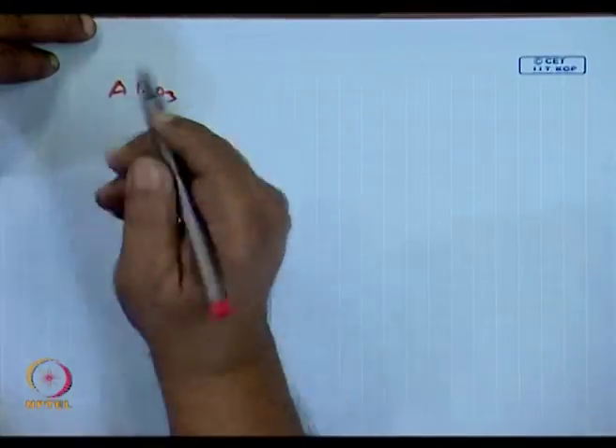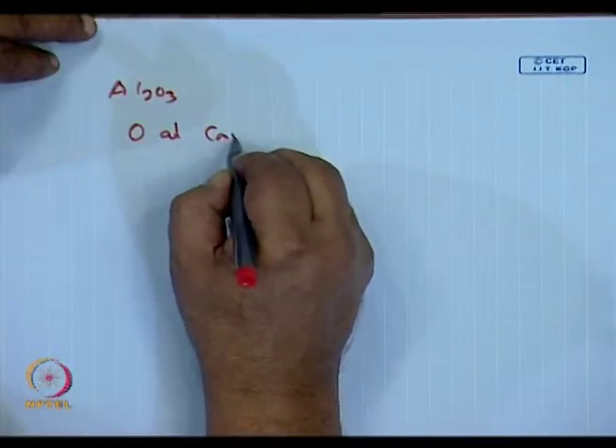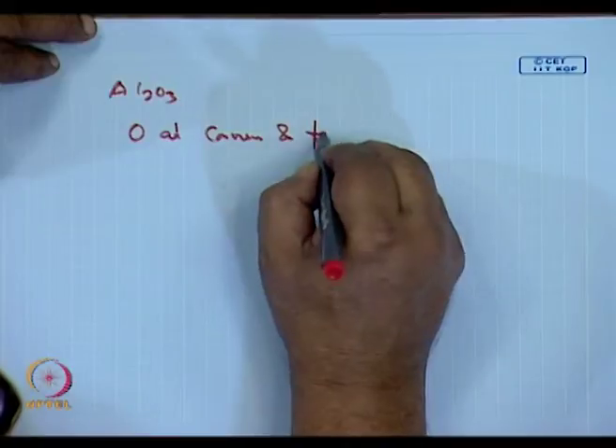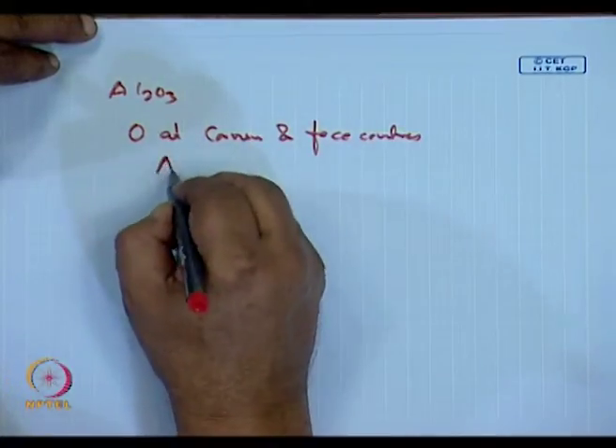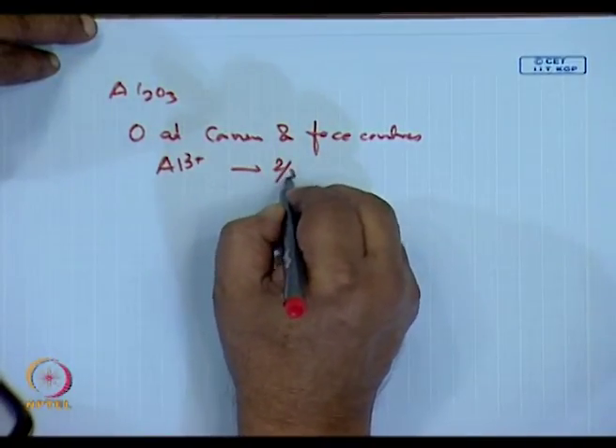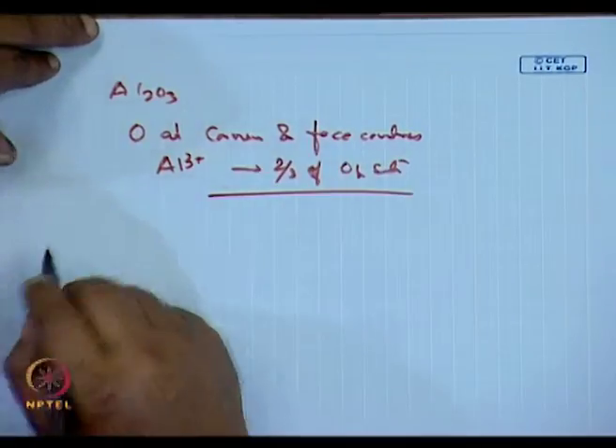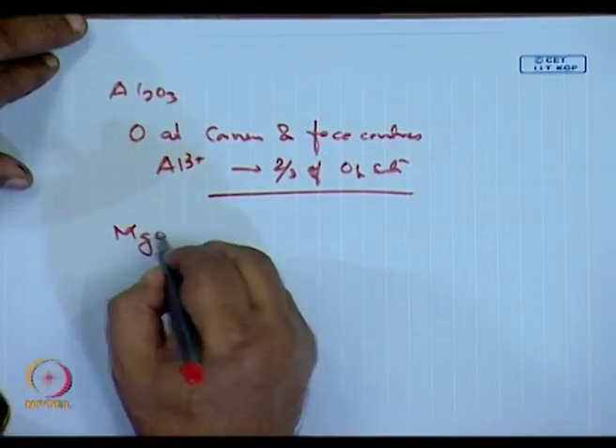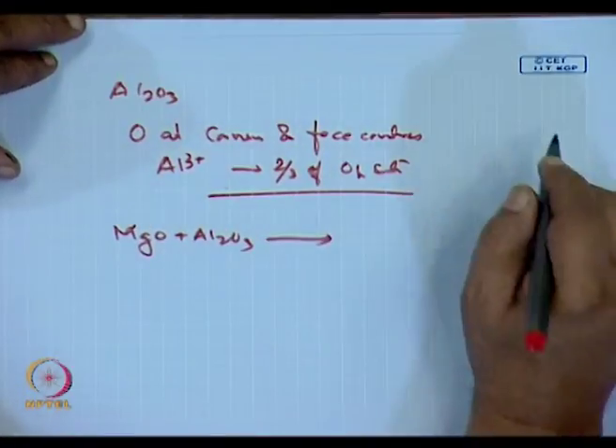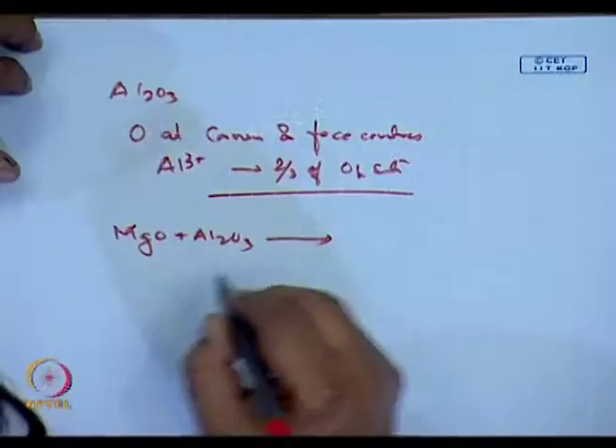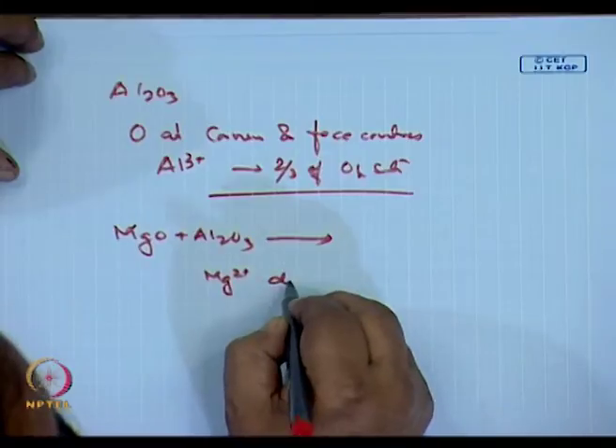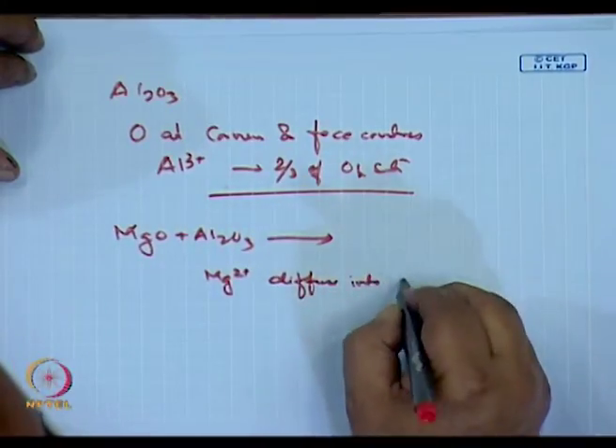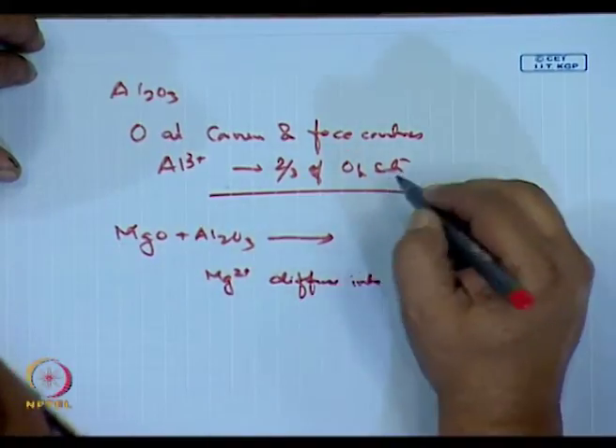For Al2O3, the crystal structure is oxygen at corners and face centers, and aluminium ions occupy 2/3 of octahedral sites. For the reaction of MgO with Al2O3, for simplicity's sake, let us presume that Mg ions diffuse into Al2O3. Why? As the tetrahedral sites in the alumina lattice are vacant, the size of the magnesium ion is just correct to fit in the tetrahedral site.